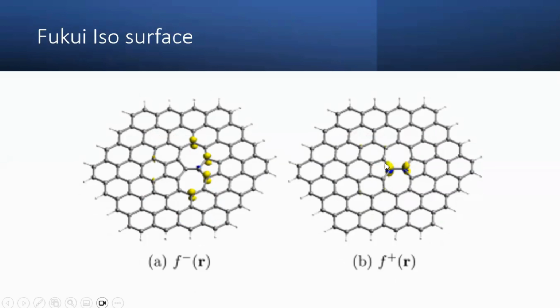But after the addition of the electron, the maximum electron cloud density is changed here. That means if there is a Stone-Wales defect, the two carbon atoms which are rotated 90 degrees have a maximum probability to receive the electron and less probability to have the electron removed from those sites.